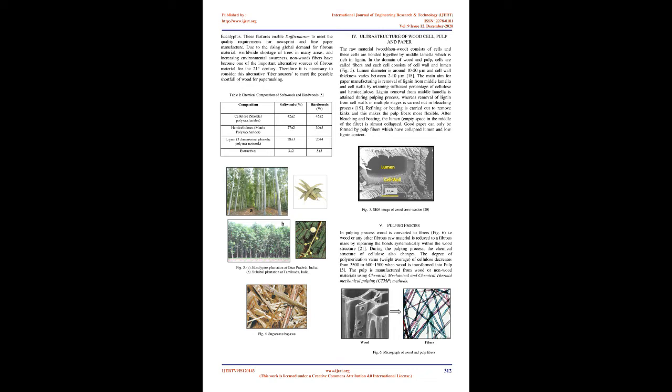The biggest difference between the species is that hardwood contains more cellulose and hemicelluloses, and less lignin than softwood. Table I. High yield and less lignin content are necessary to attain a compromise between cost and quality. In view of this, Indian pulp and paper industries are mainly focusing on wood species that have less lignin content and faster growth rate. The wood fiber species widely used for paper making in India are eucalyptus and subabul, and they are the first and second largest fast-growing trees, raised in plantations.